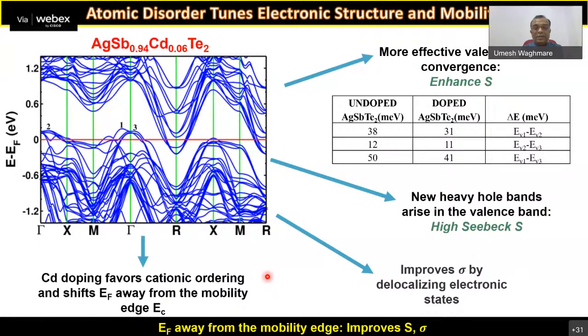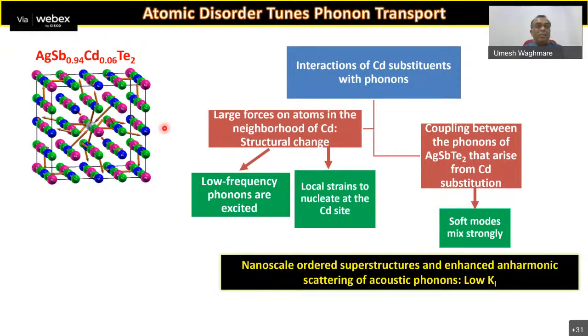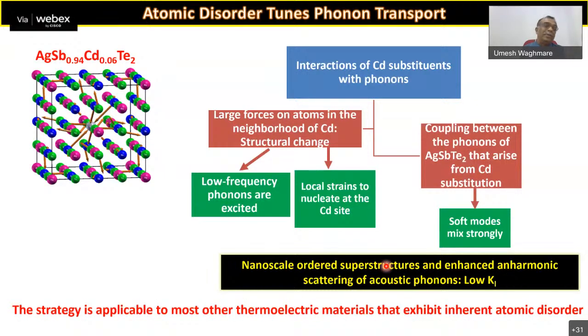So this was the idea, and as a result, we also showed that once you substitute cadmium in this crystal, it distorts the lattice locally because the size of cadmium is different. These arrows indicate displacements of atoms near cadmium, so it develops a local strain. So you have a crystal where a nanoscale region is locally slightly deformed, lattice mismatched. When there is a lattice mismatch, the sound waves which carry the heat get scattered by those regions. That scattering is given by phonon coupling. So cadmium scatters phonons through large coupling between low energy phonons and the local strain developed near the cadmium site, and that reduces phonon thermal conductivity, which is the dominant mechanism.